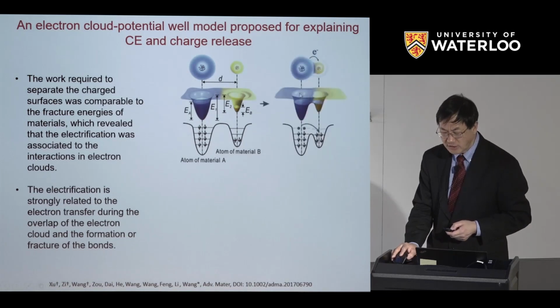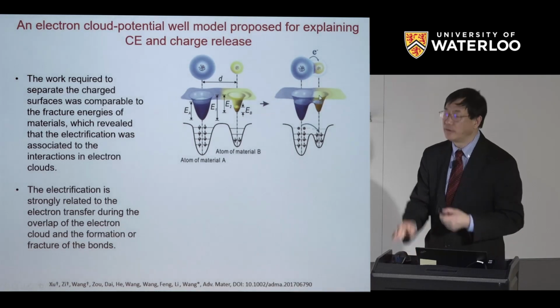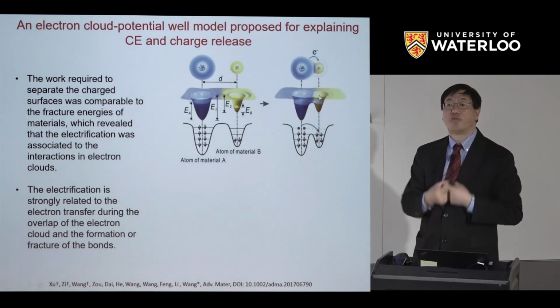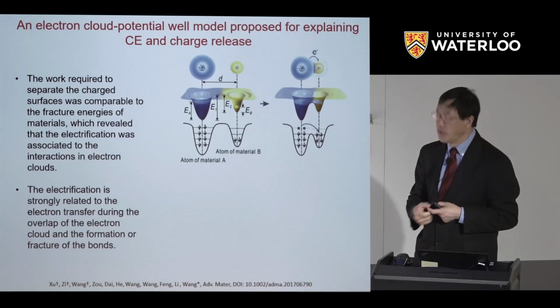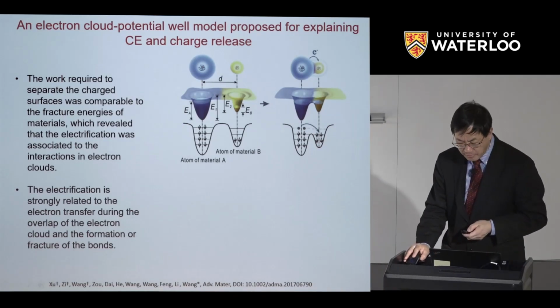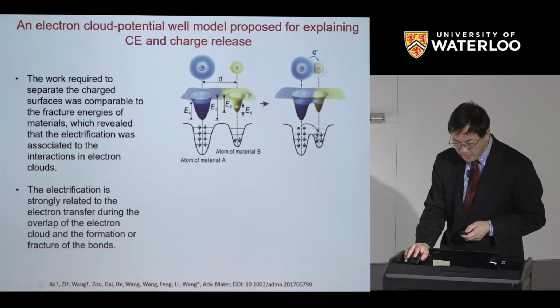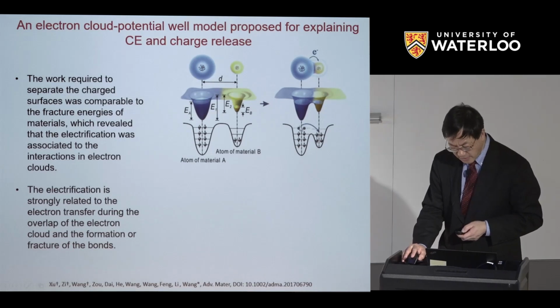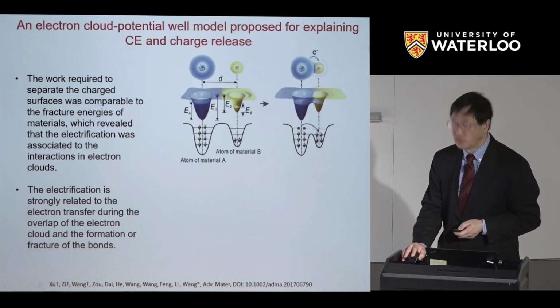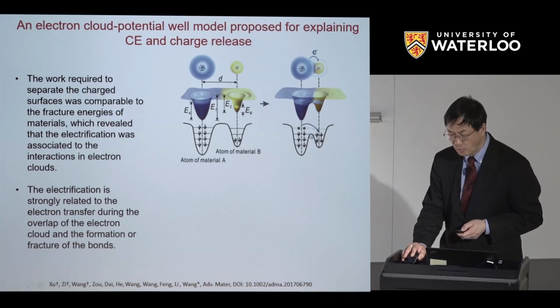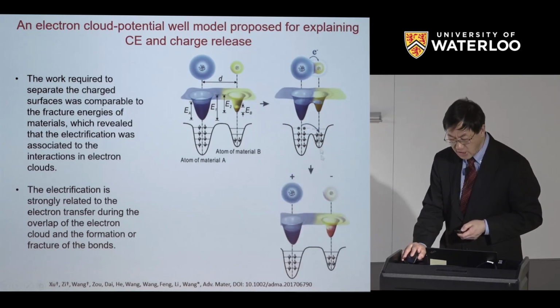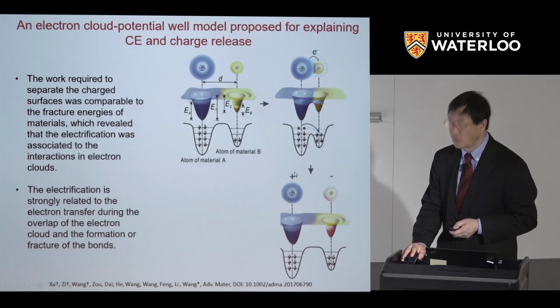However, if you rub one material against the other one, squeeze, they have electron cloud overlap. Must be. If you have electron cloud overlap, if you look at the middle point here, this barrier compared to originally becomes lower. Then there's a chance for an electron to move from here to here. So this electron jumps to here and will remain there to fill these states. If you separate the two materials, this transferred charge will remain there, so this makes a negative charge, and this is a positive charge.